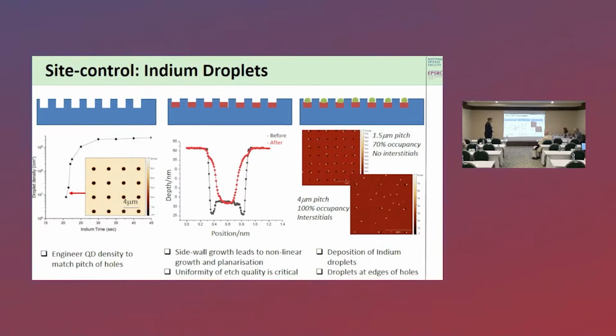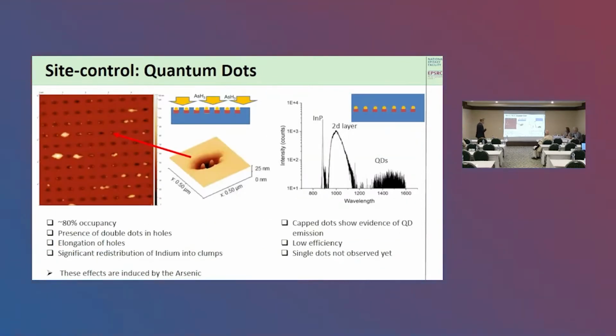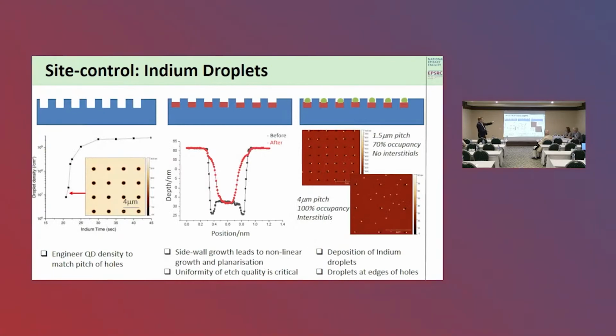A couple of interesting things that I'm not going to dwell on, but you can see actually that the droplets don't form at the center of the hole, so they actually form at the edges of the hole. And we believe this is related to essentially the contact angle between the droplet around the hole. But also there is something of a crystallographic direction to that as well. And we're not entirely sure why that is, but we have some ideas that it may be related to the etching and elongation. So I probably have about two minutes left, really. So good success. Droplets are nicely site controlled in the holes.